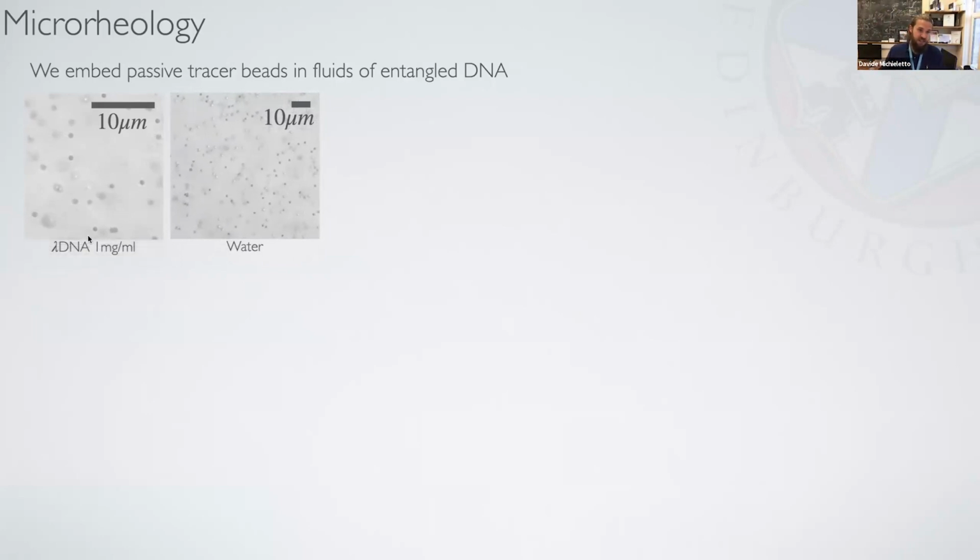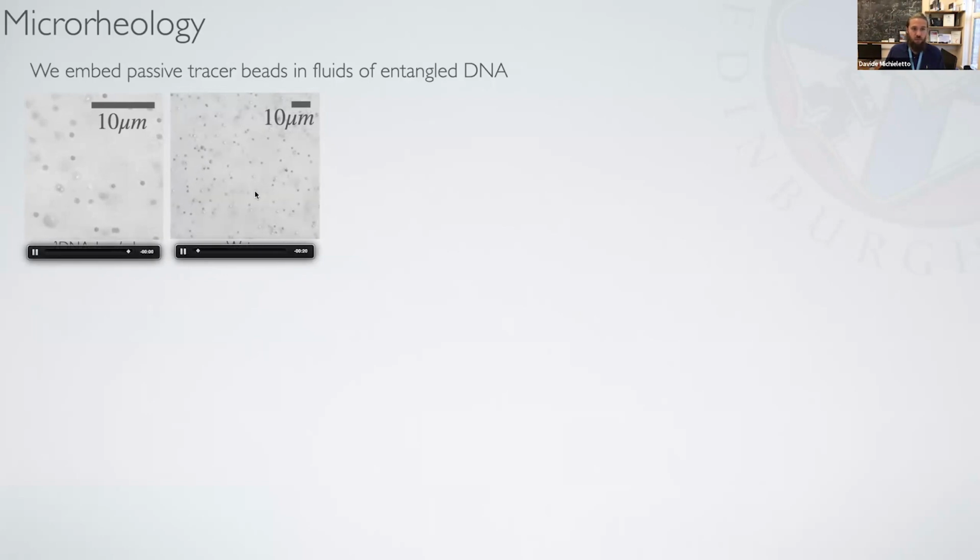And indeed, this is the point. In water they are really jiggling around, and in a solution of DNA they are stuck. There is a little bit of drift, but they are essentially not diffusing around, and this is because they are trapped in a meshwork of DNA, which you don't see because there is not enough refractive index contrast. Essentially, you cannot see the DNA. But you can see the particles, and you don't need to see the DNA.